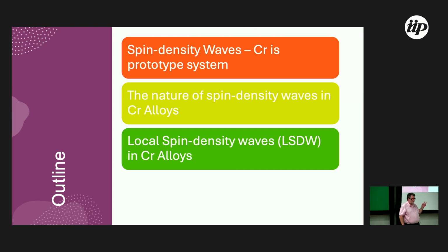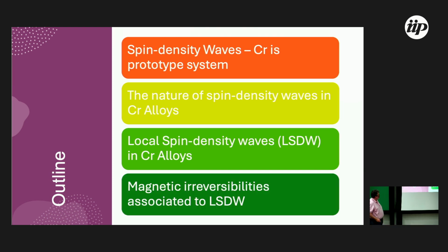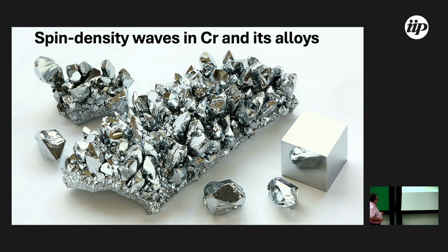The local spin density wave is an idea based on the local magnetic moments observed in this alloy. And the local spin density wave produces magnetic irreversibilities in the magnetic behavior of the chromium alloys.